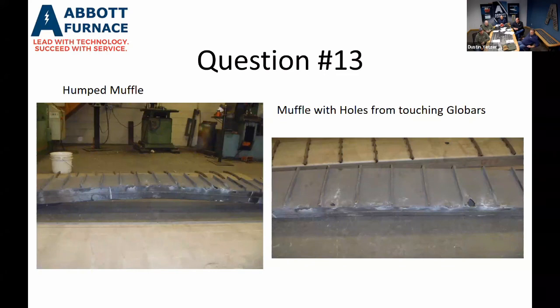We're going to ramp up again 100 an hour, and we're going to stop at 800 degrees for 2 hours. And we're going to come up to 1200 degrees and stop there for 2 hours. The important step in the process is the next one. We're going to come up to 1800, and we're going to stop there for 3-4 hours. The reason being that with stainless steel, 1800 degrees is kind of the sweet spot where, as that muffle heats up, it's going to stretch, it's going to grow a little bit. And that's where we're going to see the most growth, in that 1800 degree range, because those grains are growing. Once we get to 1800 and let that sit for a few hours, those grains are going to grow to their kind of maximum size. So after that, the grain size is kind of set in, or seasoned.